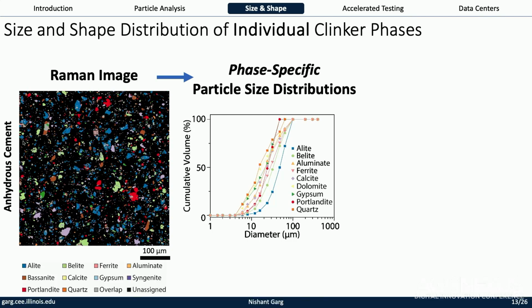We hear all these issues with type 1L cements. Well, one of my hypotheses is that the limestone inside those type 1L cements, its fineness is varying. Even though you could have two cements with 10% limestone, the limestone fineness is changing depending on how they are ground, either intergrinding or separate grinding, and so on. And this is why we see some of those variability issues, right? Anyway, that's my working hypothesis.